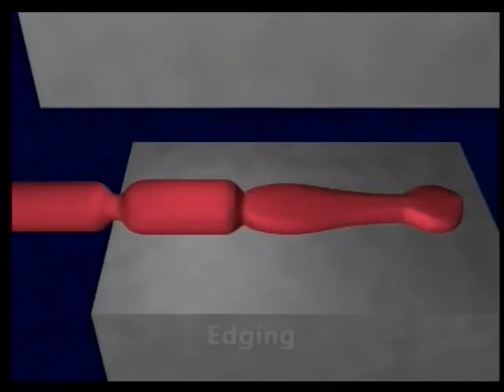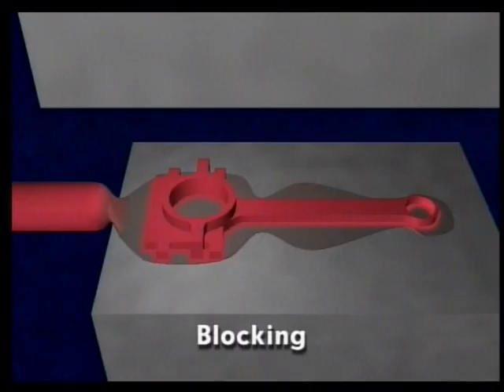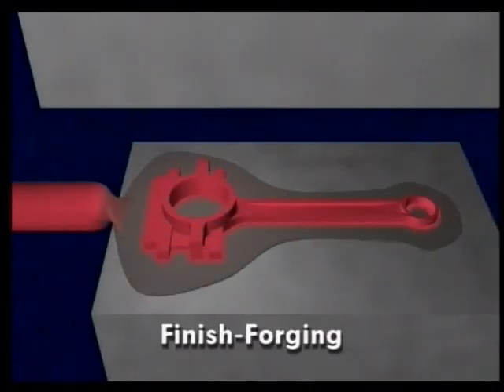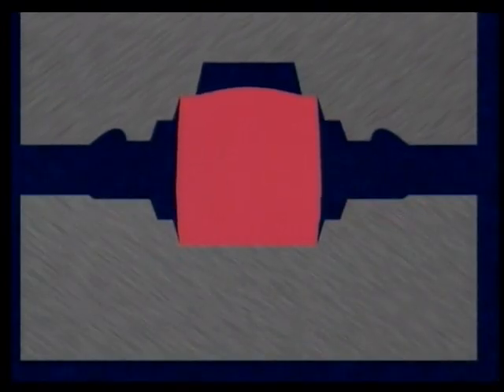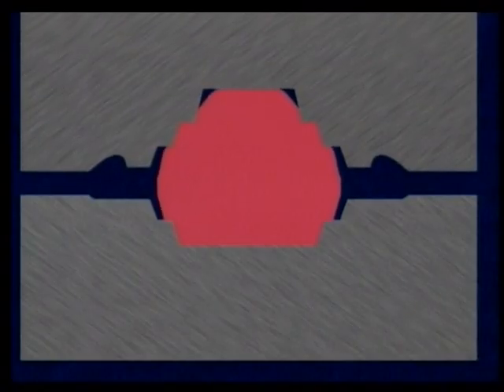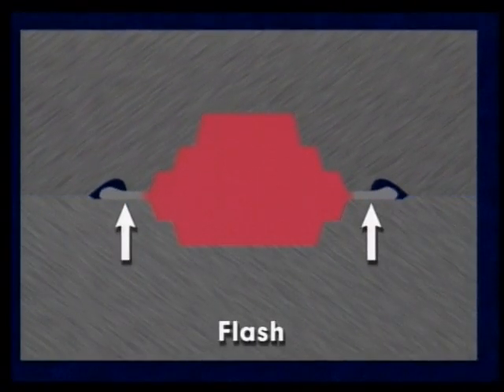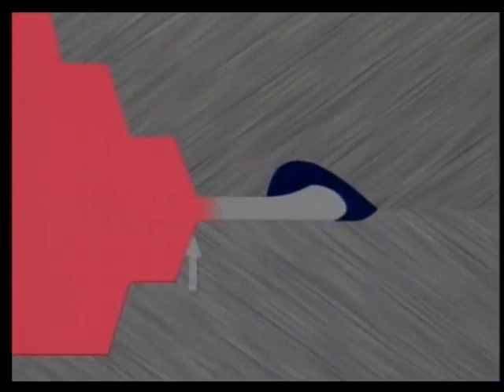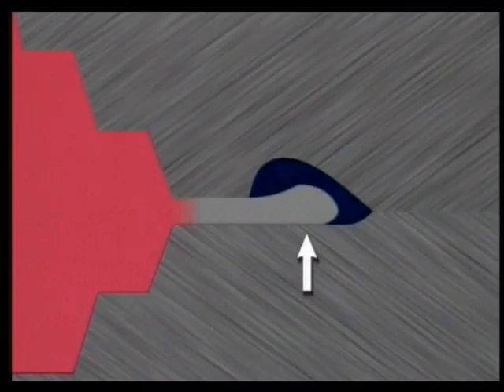Preforming operations may include edging to increase the workpiece cross-section, blocking to refine the shape for finish forging, and finish forging to complete the shape. In finish forging, the bulk of the metal is forced into the impression, while a thin layer, called flash, flows out between the dies at the parting plane, surrounding the forging. Flash comprises a flat region called the land, and sometimes a bulbous region at the end of the land created by a gutter in the upper die. The thin flash cools rapidly, increasing pressure within the impression, which assists metal flow in the impression details. Once finish forging is complete, the flash is removed either manually or with trimming dies.